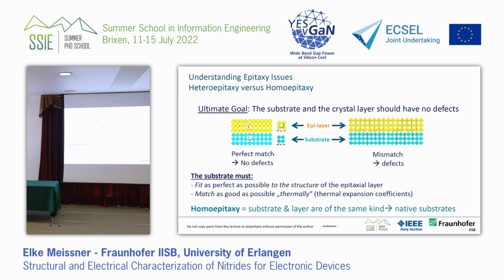Now we're getting closer to the device. We have the crystal, we have the wafer, and now we have to put epitaxy. What does it mean? The ultimate goal for a semiconductor is the same as for crystal growth. The crystal layer, which is the big individuum, one crystal lattice, very thin but large, on the whole wafer surface, must be as perfect as possible and have no defects. How can we achieve this? We need perfect match of the materials. Then we have no defects. So we have a substrate of one kind, and we have an epi layer of the same kind. Then we have no defects. As long as this is not disturbed by anything at the interface, which is cleanliness of the interface.